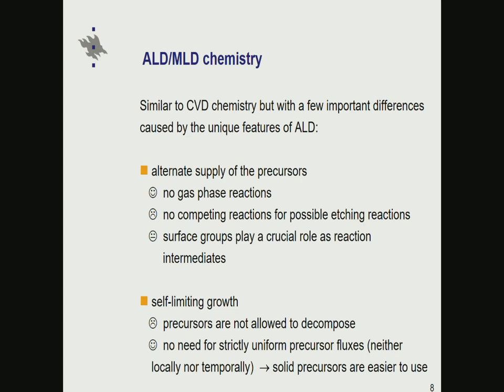Self-limiting growth has a negative side: it limits the choice of precursors, so we need to find precursors that are not decomposing on their own. If they are decomposing on their own, we lose the self-limiting growth. On the other hand, the good news is that we don't need strictly uniform precursor fluxes to produce uniform films. This applies spatially, so we can have a larger dose in one part of the substrate than in another part, as long as we are saturating all the surface reactions.